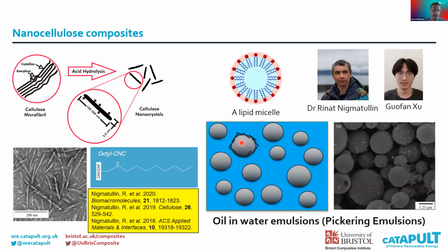Now, we've been looking at all kinds of different composites, and I wanted to just bring to your attention this particular system here that's being looked at by one of my new PhD students, Guofan Xu, and he's been making some cellulose nanocrystals. So here we take the plant material, which has crystalline ordered regions and amorphous or disordered regions within it, and we take a strong acid, and this hydrolyzes the amorphous regions more readily than the crystalline regions. So you end up with these rod-like cellulose materials, which if you do this using sulfuric acid, you get a negative charge on the surface. So these things are dispersible in water, which is quite useful for green processing.